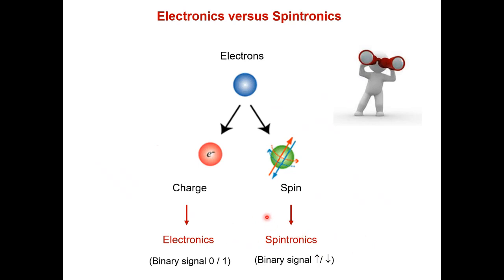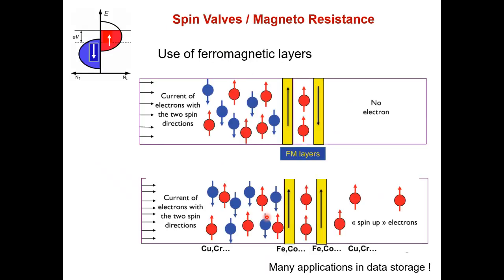So spintronics is fascinating. It's not an easy field to go into, but I can show you a simple example of what you can do with the world of spintronics. So let's say that you have a current of electrons flowing in a metal like copper, and along the way you put a ferromagnet. For many materials and molecules, if you look at the number of electrons at each energy, typically you have the same number of spin up and spin down at whatever the energy is. In a ferromagnet, it's different, because you see that for some energies you have a lot of spin up but no spin down. So you have a spin polarization in the material. And it goes like that: when this current is flowing across the ferromagnetic layer, only the spin parallel to those at the Fermi level can cross this layer.